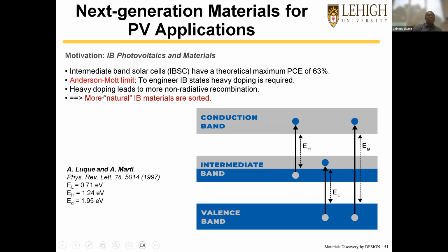Generally, for any intermediate band system, the Anderson-Mott limit is required to engineer an intermediate band state. And what does this mean? It means a highly doped system with strong interaction combined together. So heavy doping, but this heavy doping generally leads to more non-radiative recombination, which is known to destroy potential photovoltaic application due to recombination effects that quench radiative recombination.